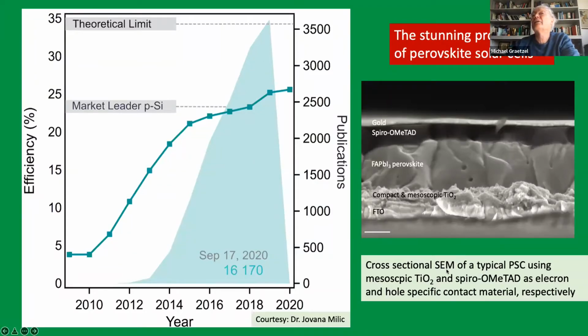And here on the left, you can see the typical cross-section of the perovskites. These are the so-called NIP version, where the N means the electron collecting negative electrode. The negative electrode is the TiO2 here, and still mesoscopic, the same we had used for the DSC. And light comes in through this N contact, so it's called the NIP. And so we have the mesoscopic contact that is electron selective, as it was for the molecular system. But then you fill up the pores, and you have a capping layer that is becoming now the main light absorber. This is this bulky part you can see here. And then there's a hole collector. You need a hole selective contact.